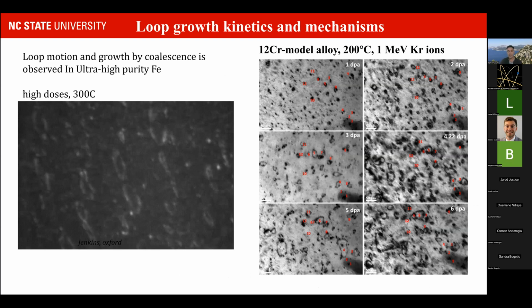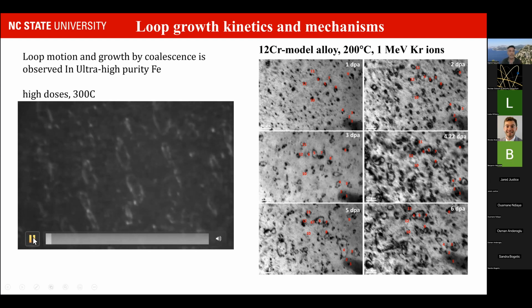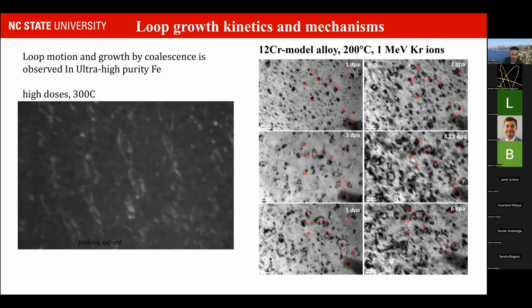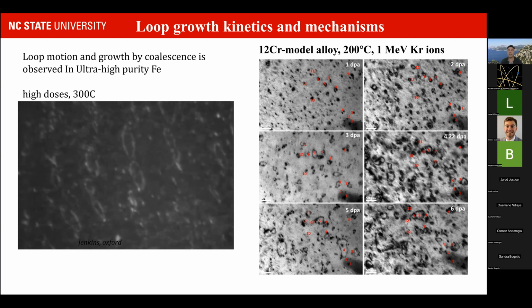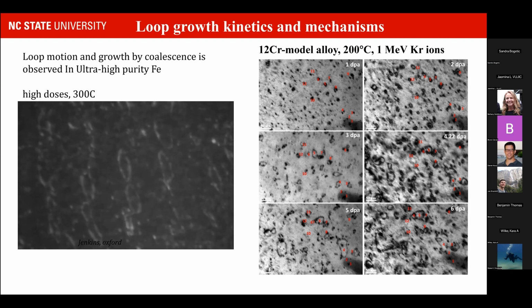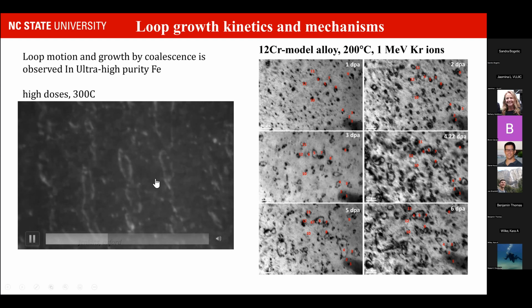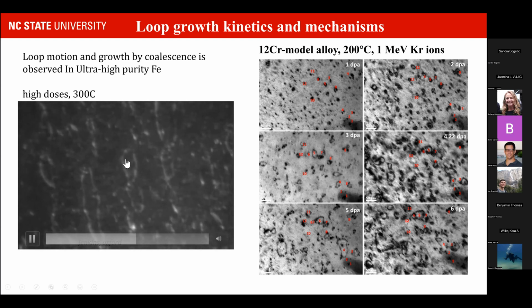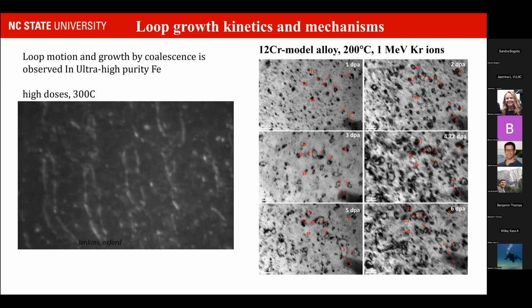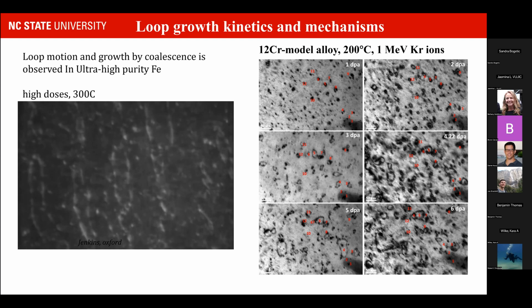Another interesting aspect that we can see with the in situ irradiations is to learn about mechanisms of loop and defect growth, for instance, and the effect of the material composition. So for that matter, I'm going to show you on the left an experiment that was done by Jenkins' group at Oxford in the exact same facility that I'm talking about and that I have used myself. And they were working on ultra high purity iron. And what you see here is also this dynamic picture of the radiation damage, but I would like to draw your attention to those loops that are growing, and some of them are even able to move so that they can coalesce. And you see those large finger-like features in the end. This coalescence of loops will account for the kinetics observed in ultra high purity iron.